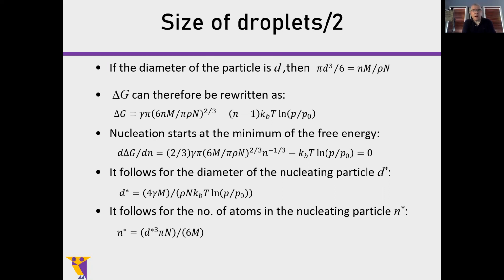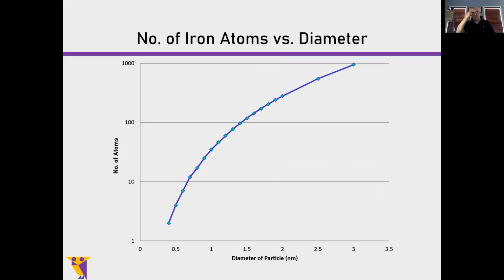And it turns out for iron, and iron is used because, first of all, it's cheap. Second, it's not toxic. It's better than using cobalt or nickel, or in some cases, ruthenium, which I won't get into. You can generate droplets of iron about half a nanometer or so in diameter that are stable at these temperatures and pressures. And that's important because when we start getting to about 100 atoms, which is sort of the cutoff, we're at a diameter of about 1.5 nanometers.